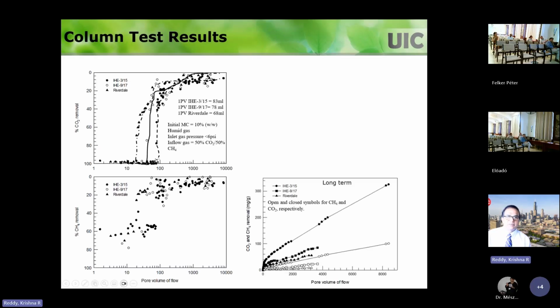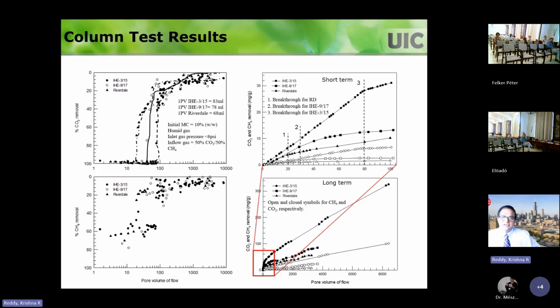And you can see the column experiments. You won't see anything coming out for many pore volumes. You need 100 pore volumes to see any kind of CO2 coming out. So the material will exhaust, not like a biochar amended soil where biological reaction can keep on going. But in this one, the capacity is limited by how much carbonation that the material can take. So this slag will have a finite life in terms of its reactivity. And you can see how much cumulative CO2 is removed. And you can look at these profiles and you can understand the mechanisms of what's happening at different stages.